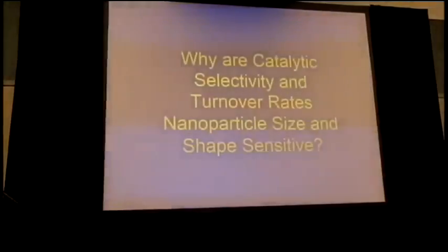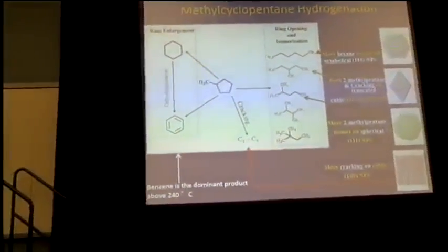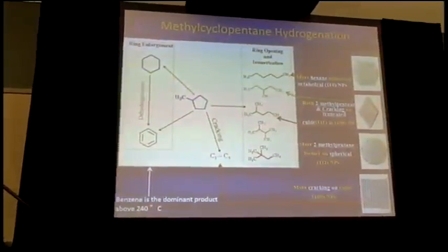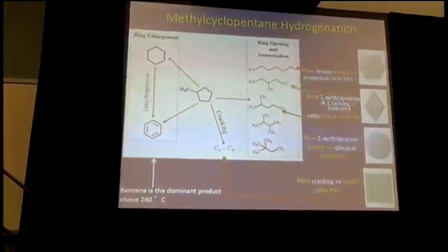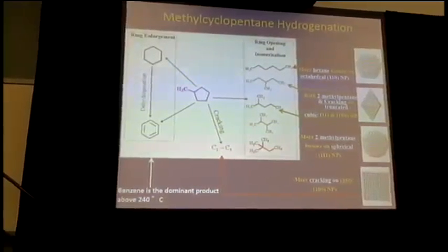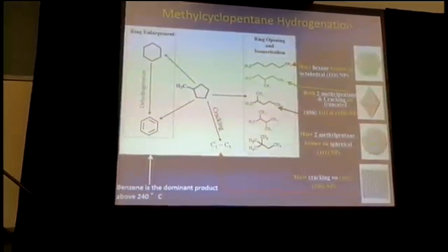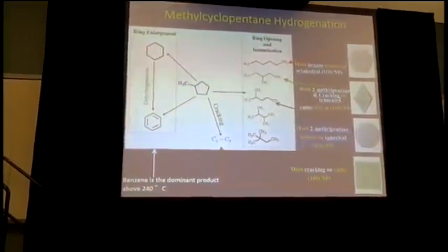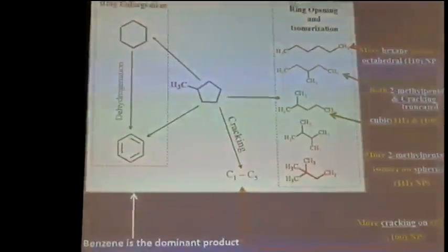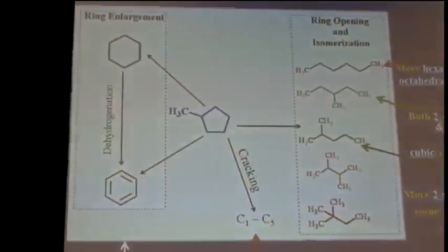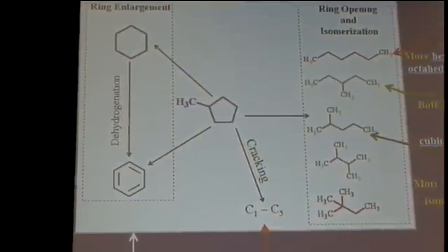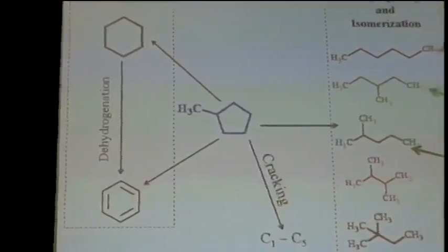And so let me give you one shape-dependent catalysis, and this is methylcyclopentane. Methylcyclopentane can isomerize in all these isomers. It turns out that when you change the shape, the isomer you get is shape-dependent. Okay, a very interesting case. The turnover rate doesn't change much, but the product selectivity changes dramatically. Now, the question is why? Why is selectivity and turnover rates size and shape sensitive?